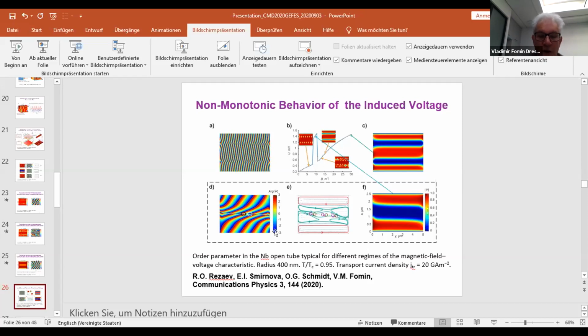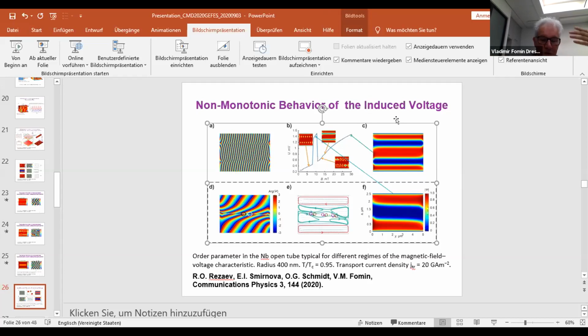And this peak is for the niobium tube with parameters which are shown here. I hope you can see them. This peak is threefold. When we further increase the magnetic field, so we can enter the double chain regime, this generation of the induced vortices goes back to the origin due to moving vortices in the upper and lower turns. And still at higher magnetic fields, this motion becomes faster, but in this case, these are moving vortices.